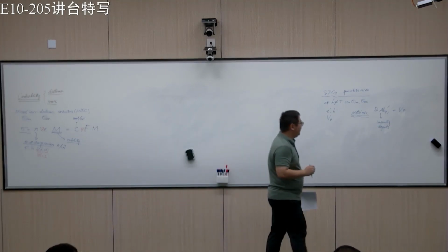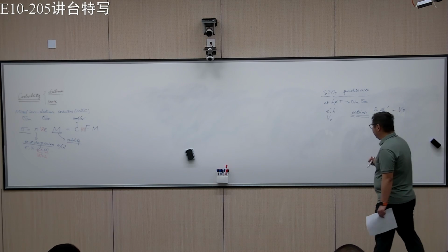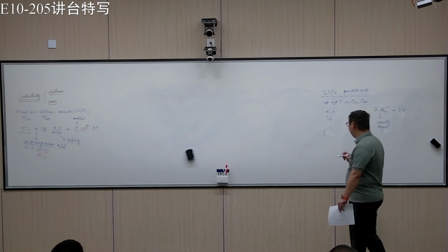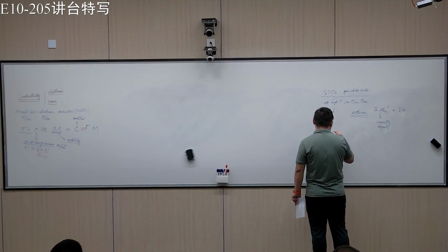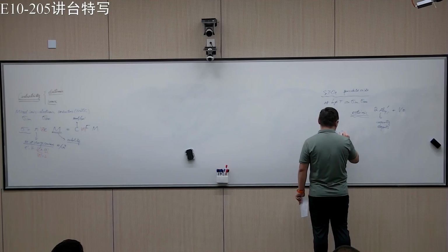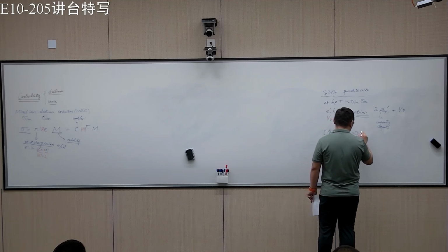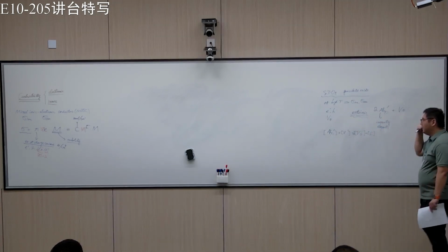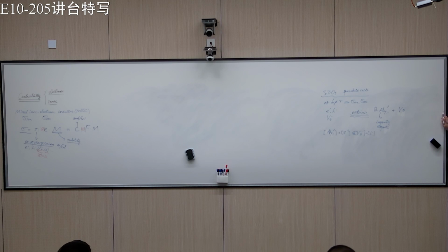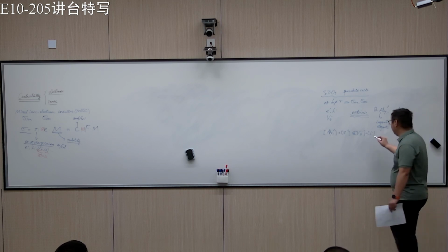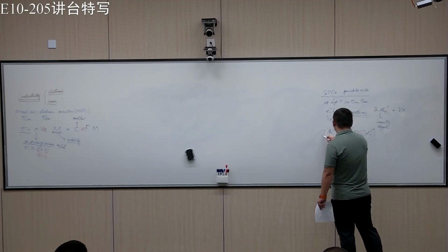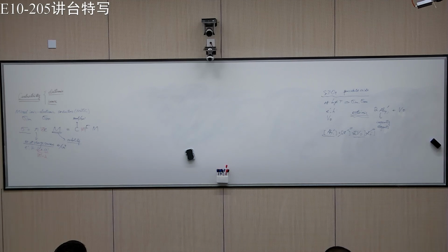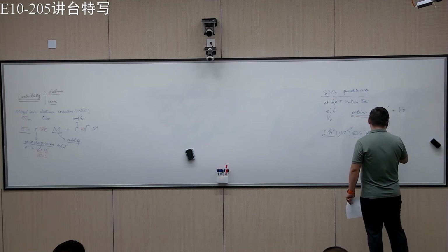We can think of a bunch of defect configurations, but first let's think of the charge neutrality condition: all the negative charge defects, aluminum, balance the positive ones. In this system, the band gap is very large, which means that we can safely ignore these two. All we need to think of is basically this one. This is the boundary condition.